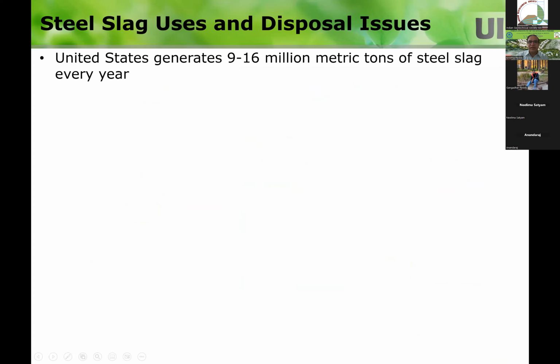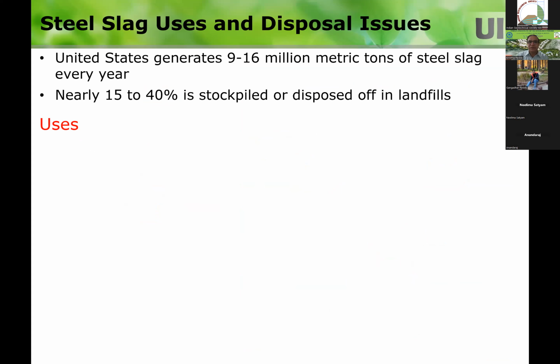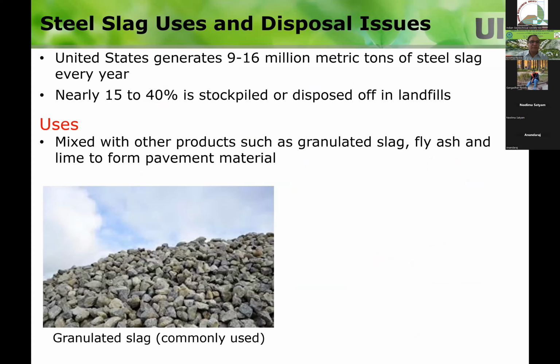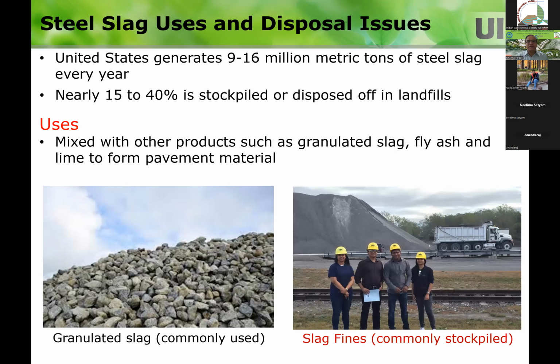And why did we pick the BOF slag? Because we have steel plants right next to Chicago, and they use the bigger size slag particles as a hard material for pavements. They are selling that one extensively. But the problem is the finer material that they get out of this, as you see the piles of these in the back, that have no uses. So this coarser material is used as an aggregate material, but these slag fines are commonly stockpiled. This is the steel plant close to the site.